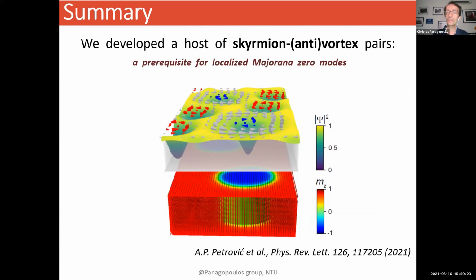There is a challenge, as I showed you earlier, that you have this platinum on top in order to avoid oxidation. But ideally, and it's doable, if you have the niobium on top of your skyrmion and vice versa, you can look at the core of your superconducting vortex or anti-vortex and look for the possibility of Majorana modes in the zero bias anomaly. But there are also other methods that one can actually try, transport methods that we are trying to develop.